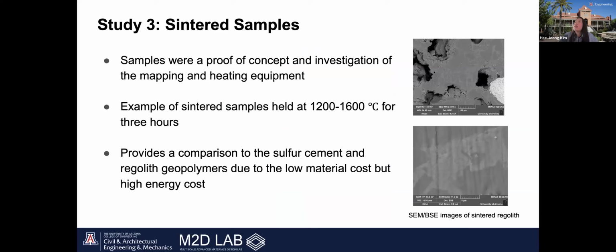And lastly, our lab has been exploring the use of regolith sintering and melting to create small-scale parts. These approaches are especially interesting because they use the regolith powder directly without any additional processing or binders. In our experiment, regolith simulant was heated to 1200 degrees Celsius and 1600 degrees Celsius to sinter and melt the material, and the resulting samples were then characterized using Raman spectroscopy and SEM microscopy to study their microstructure and phase composition. The long-term goal of this study is to apply laser powder bed fusion to additively manufacture complex parts directly from lunar regolith powder, enabling on-site fabrication for future space applications.